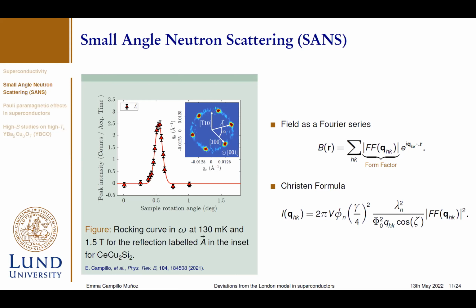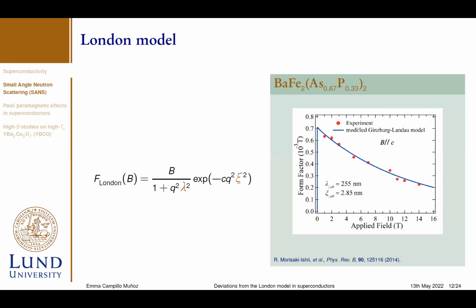So if we express the magnetic field that is passing through our sample as a Fourier series, the Fourier components are known as the form factor. The integrated intensity that we measure in our experiments and the form factor are proportional to each other. So we will be able to characterize this superconductor by the dependence of this form factor when we apply certain temperatures or different fields.